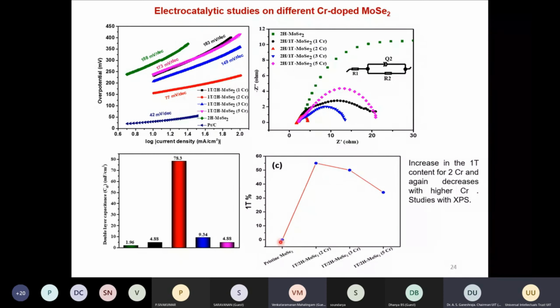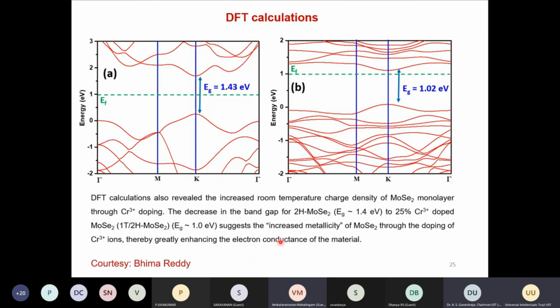And we then tried to understand why this chromium doping helps in increasing the activity of the hydrogen evolution reaction. We have done DFT calculations, which reveal an increased charge density of the MoSe2 monolayer through chromium doping. What we can see here is basically that the band gap decreases. You see the band gap compared to this; this is the chromium sample, where the band gap decreases. Also the Fermi level becomes close to the conduction band. That means there is an increase in metallicity, which increases the conductivity, which is good for the catalytic process.